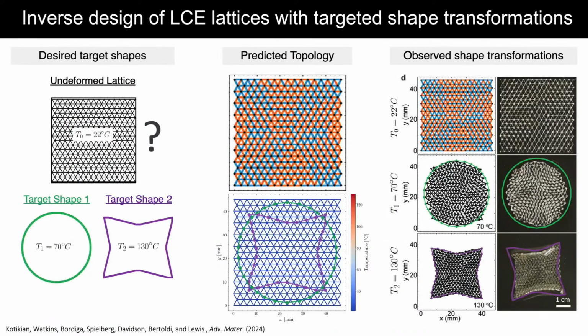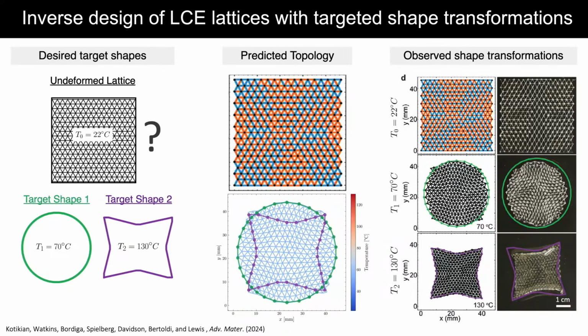Okay, so with that in mind, we used that model that Audrey developed to create something a little more random, it looks like in practice, where local regions may be more rich in low TNI or high TNI. But the idea was that this lattice architecture would shape morph sequentially from first a target shape at an intermediate temperature, where just the low TNI filaments or struts morph, to this four-arm star. So let's see if this is what we predict would happen from the model.